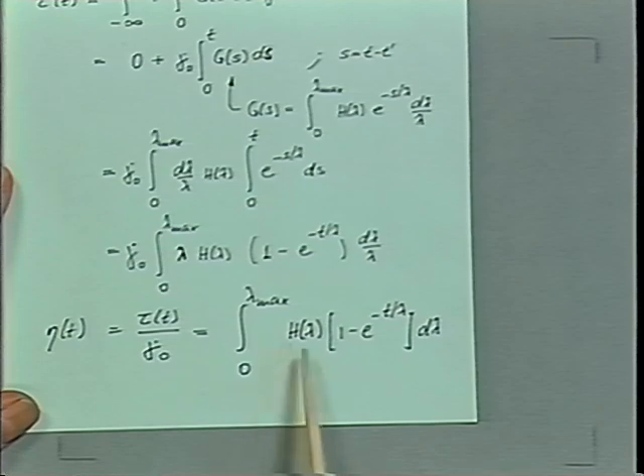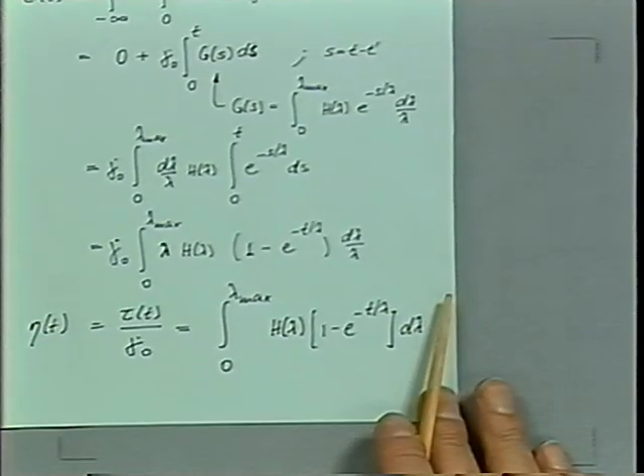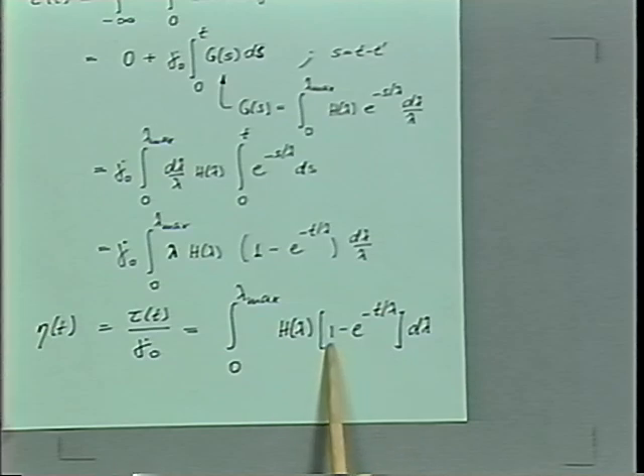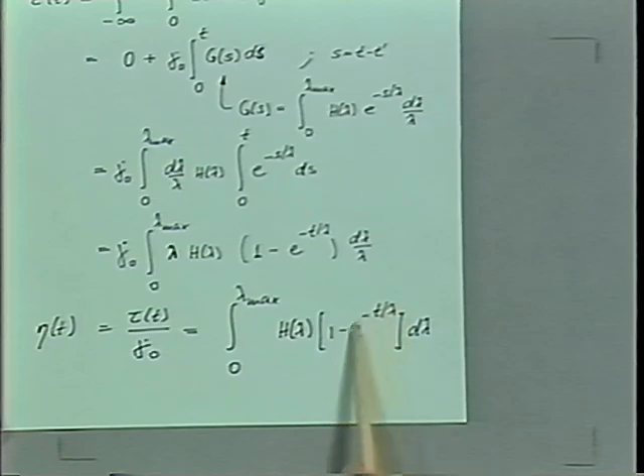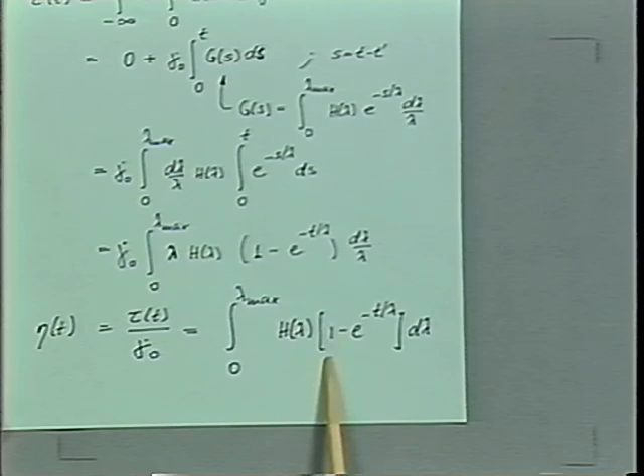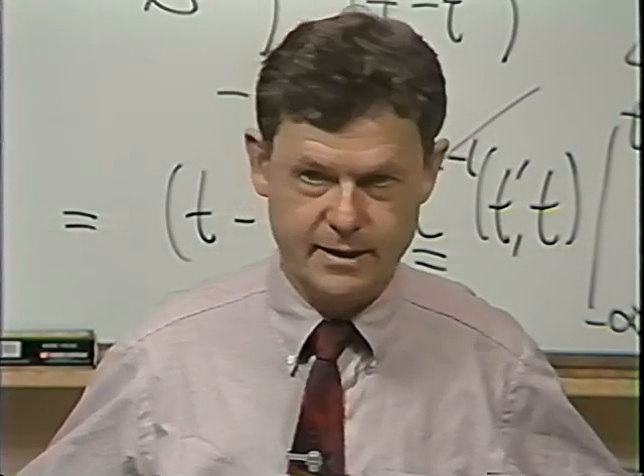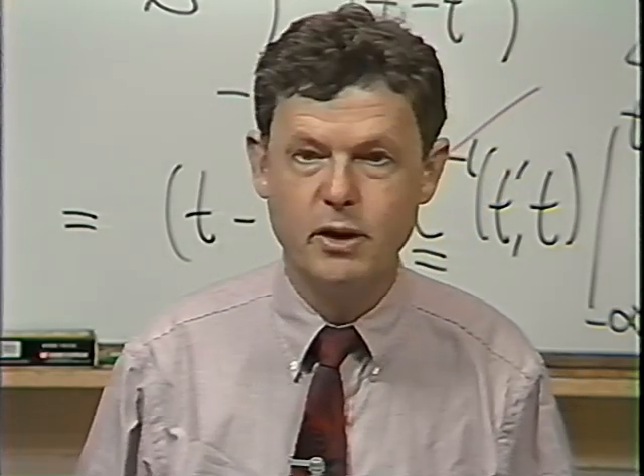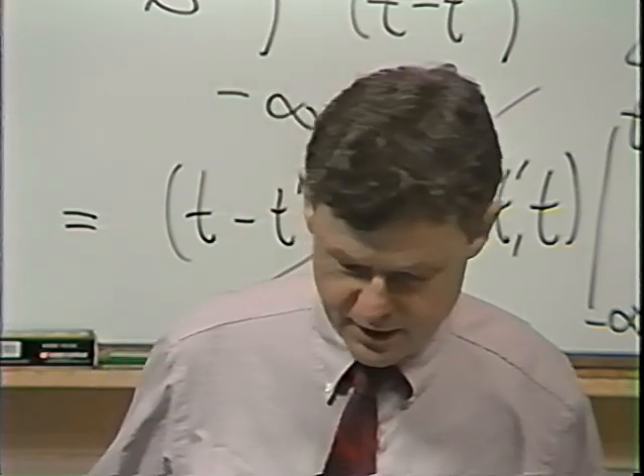Now note if the longest relaxation time is infinite, here we might get into trouble. And this comes up in the following way in this integral. The first part is giving us the steady state contribution. And the second part is subtracting because everything is transient. So when the transition of the startup is over, this contribution is 0. In our gel, we will have a contribution here which is infinite. If the steady state viscosity is infinitely large, then this is infinite, and then we subtract something from that. So in the solution, we have to watch out for trouble like that because of this divergence of the longest relaxation time. This might give some problems.